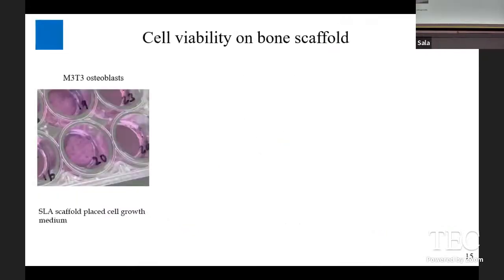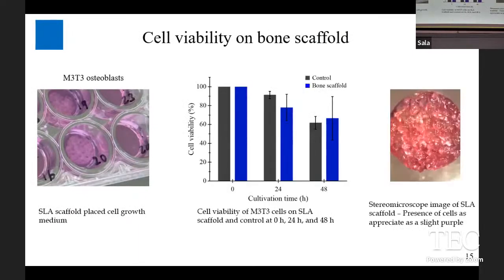Now I will move into the cell viability of the bone scaffold, because as I said, we needed to test cell viability. So we did some growing of bone cells on some pieces of the bone scaffold and tested the viability, which means how many cells were present after a period of time. And we compare with a control that were cells that were growing without any scaffold. As you can see, both of them behave in a similar way. That is a nice result because it means that the scaffold doesn't have a negative effect on the cells.